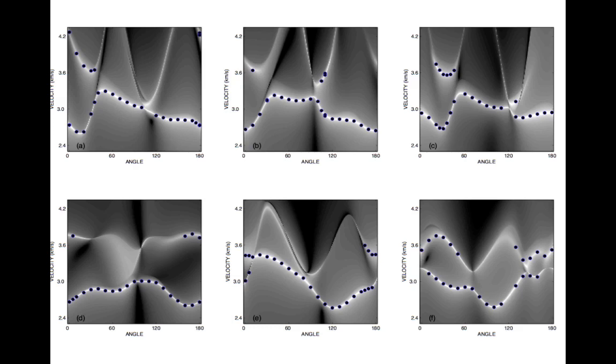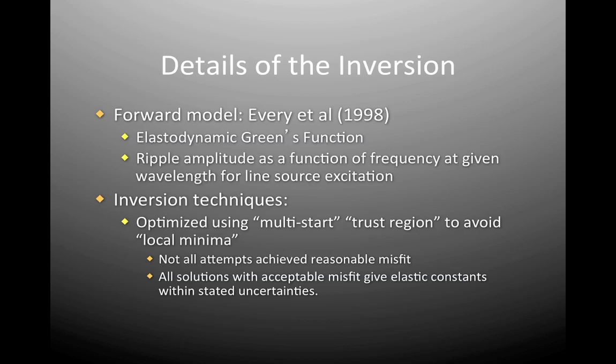Good fit represents high amplitudes matching the location of measurements, and you can see the very light color represent peaks in the theoretical calculation, and we observe surface waves at frequencies that match where the calculation showed high intensities.